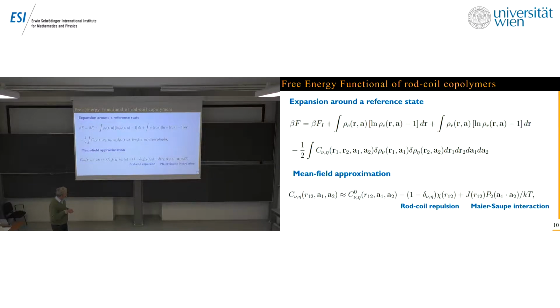And so this means that we approximate our correlation function as C0 within one chain, and then the interactions between chains which we would like to take into account. And here, of course, there are models. So we adopt just a standard Flory-Huggins approach with later works, where people take into account only two types of interactions.